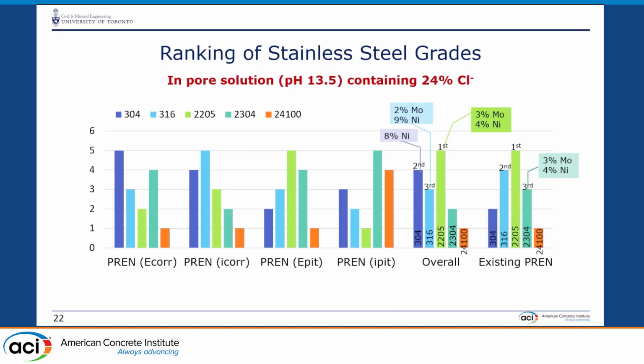We had an overall ranking. We used it for a case study in pore solution pH with 24% chloride addition. This would be the overall ranking. And if you compare that with the existing PREN number, you can see there's some positional change as to which one ranks first, second, or third. So 24-100 consistently ranked lower.